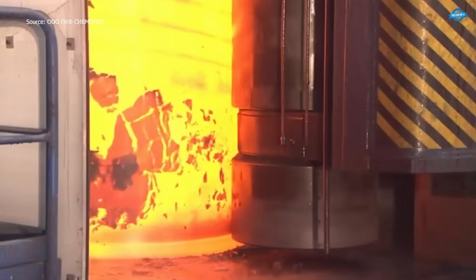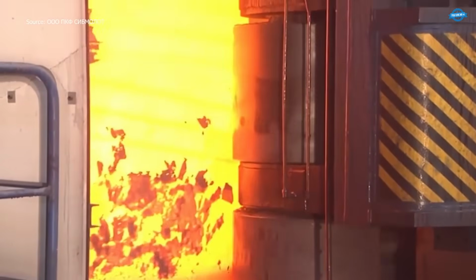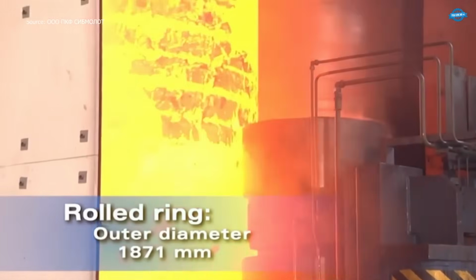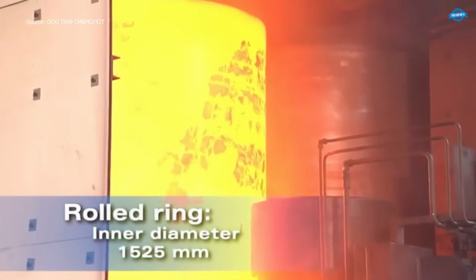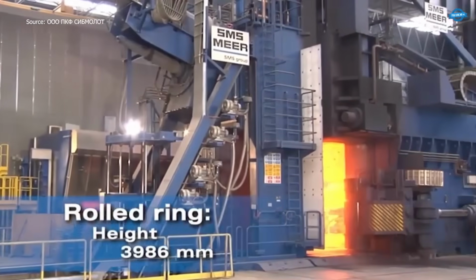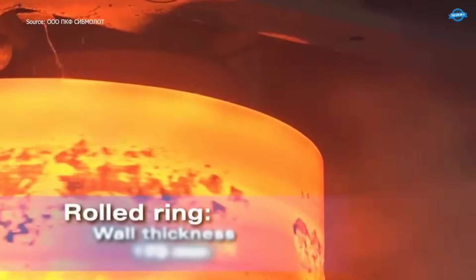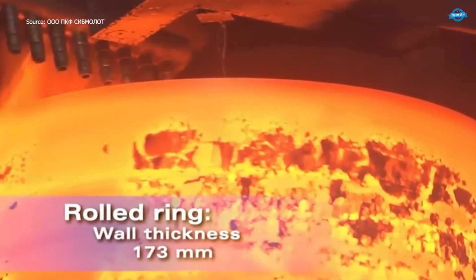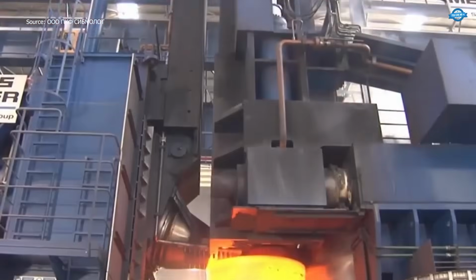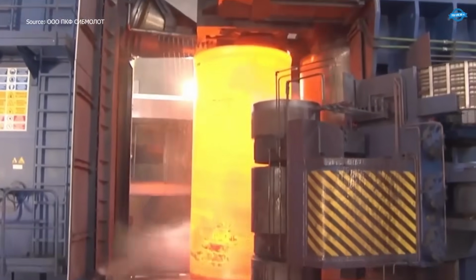Once ready, the radial-axial rolling machine engages, gradually forming the ring over 214 seconds. Height reaches 3,986 millimeters, with a wall thickness of 173 millimeters, while sensors and guides constantly maintain the correct profile. It is impressive to witness such massive components undergo controlled deformation.